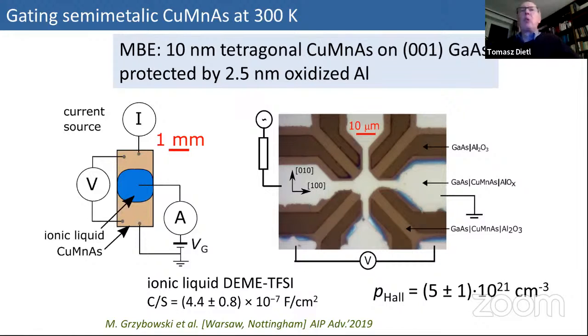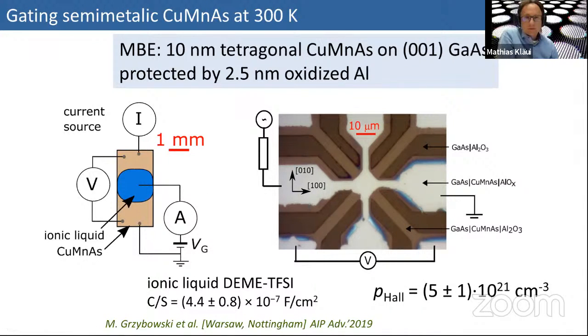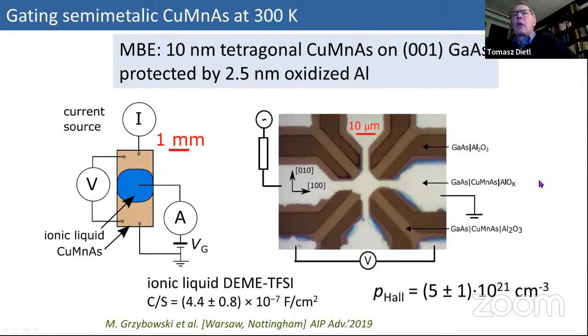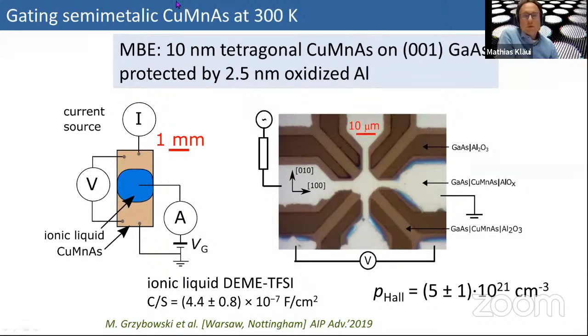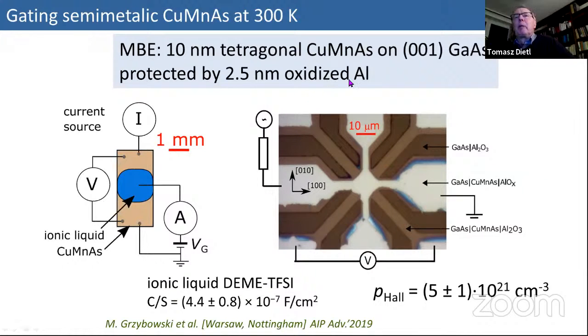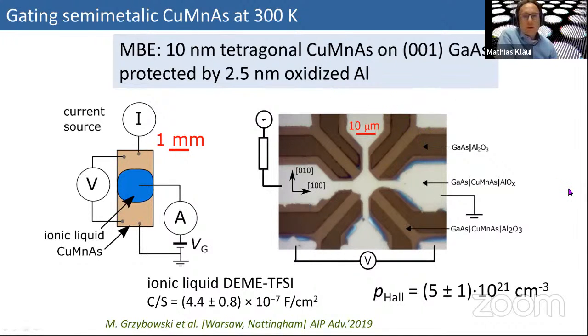Yeah, we protect the material by aluminum oxide, and then we use ionic liquid to produce the electric field. We protect the material from chemical reaction with the liquid by oxidized aluminum. And I wonder how much it is really oxidized through, because 2.5 nanometers of aluminum usually doesn't oxidize all the way through. Aluminum is very conductive. So I'm wondering if the effect in reality is much larger and you just get a lot of screening from unoxidized aluminum at the interface between the copper manganese arsenide and aluminum.